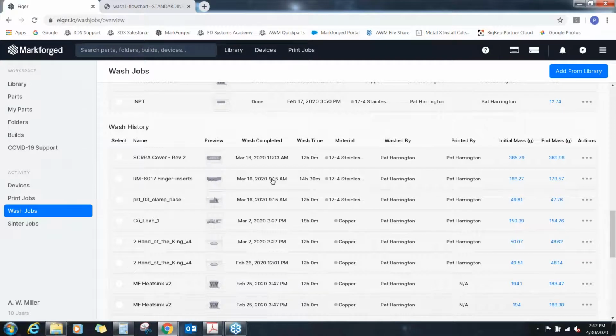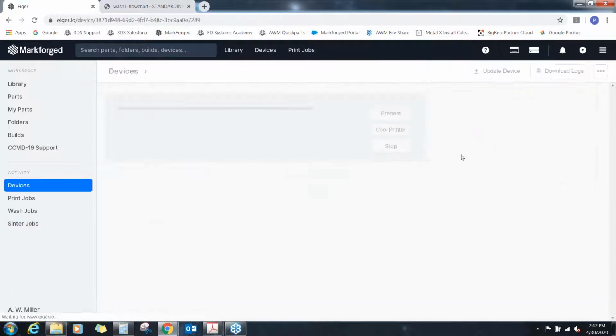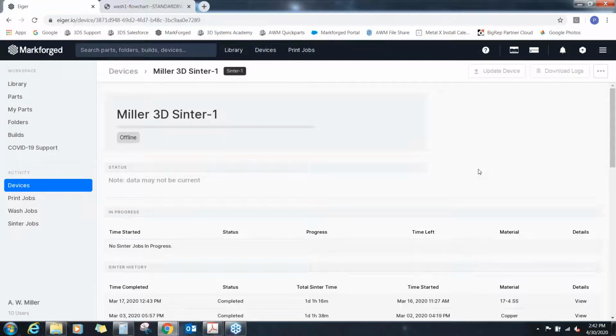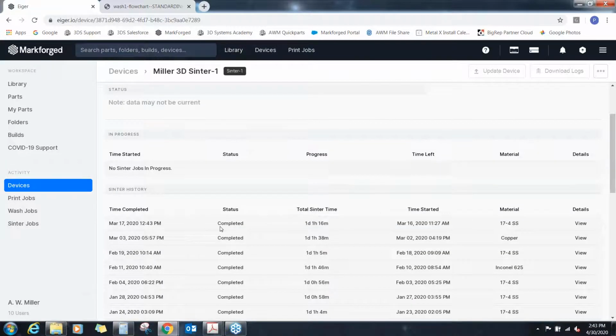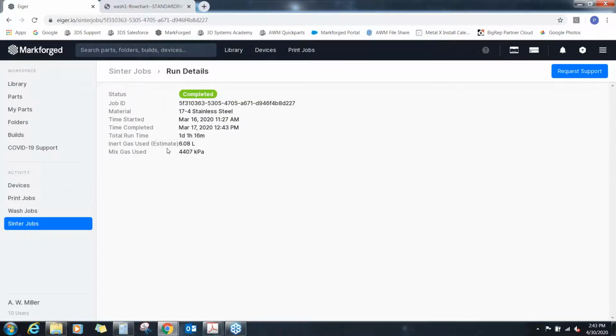As long as you get the okay from Eiger, you can put your parts into the furnace. The sintering process is controlled on the unit itself, but it can be monitored from Eiger. The run duration is really just a function of the material that you're running. It's not governed by how many parts you have in the furnace. It's just a function of what material you're running, so it's always better to load up the furnace with as many parts as you can to keep your per part cost down. And then those runs can be monitored from Eiger software. So if we look at this part here, this is a 17.4 run we did. It's going to estimate how much gas usage, inert gas we used, as well as our forming gas that are used in this process.